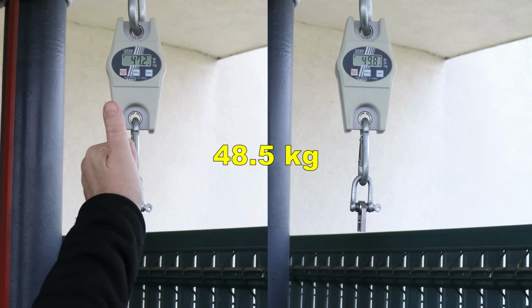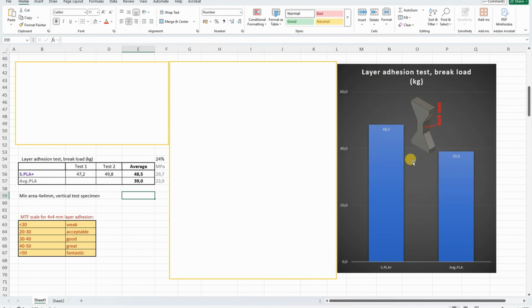Layer adhesion with vertically printed specimens. Quite strong. In this test, completely different story. The Super PLA Plus is stronger compared to the average PLA by approximately 24%. And here you can see my rating for this test object, so this means it has a great, almost fantastic layer adhesion.